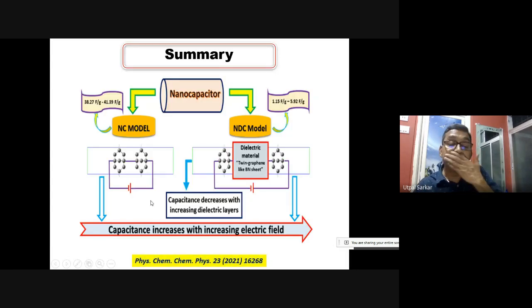So, summary. Basically two types of model we have discussed: nanoscale capacitor and nanoscale dielectric capacitor. For the nanoscale capacitor, the capacitance is very large, around 38 to 40 farad per gram. However, for the nanoscale dielectric capacitor it is of the order of 1 to 6 farad per gram, and capacitance decreases with the increase of the dielectric layers, and capacitance increases with the increasing electric field. This is the summary of this work.